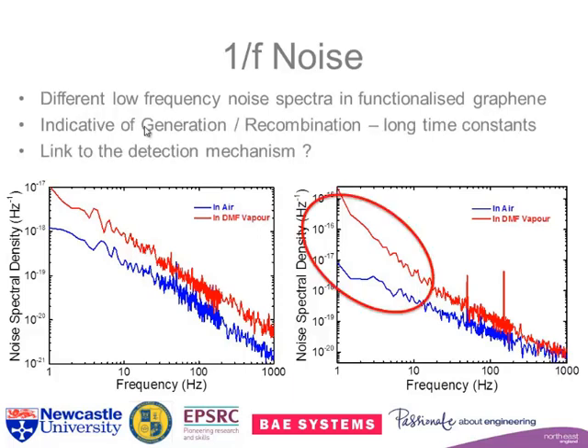However, this bit shows something slightly different. Down here, we see a 1/f squared behavior once we get below 25 Hertz, whereas this here is 1/f, as it is here for the whole frequency range. This is something different. This is indicative of a generation recombination mechanism that's been published before, and we think this comes back to detection. However, these are very long time periods. We're talking, things with a time period of 100 milliseconds to a second. It has to come out to chemical kinetics. We think it's the absorption and desorption of material on the surface.